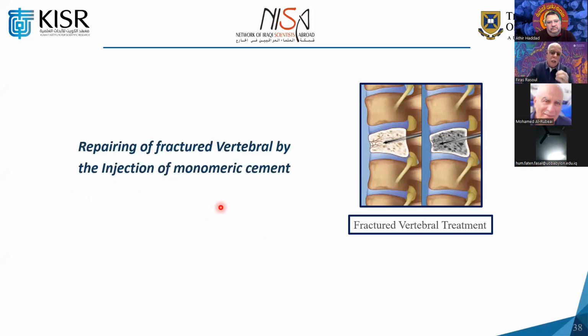Plus, when the polymer cures, it produces very high temperature, above 55 degrees centigrade. And this is an exotherm temperature, and this exotherm temperature might cause necrosis. It might kill some of the tissues surrounding the vertebra. So there is a major disadvantage of using it.